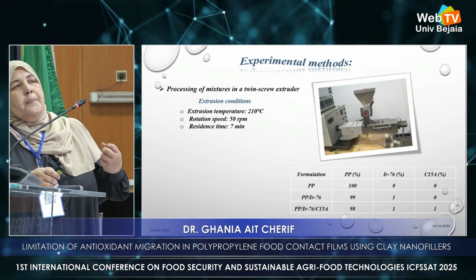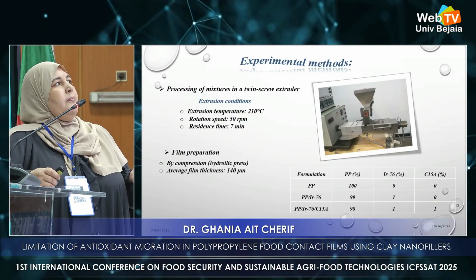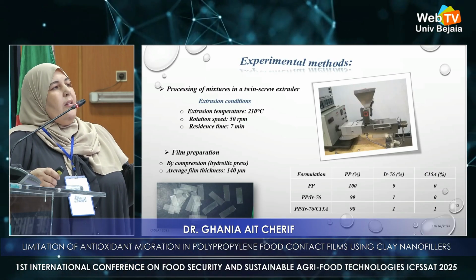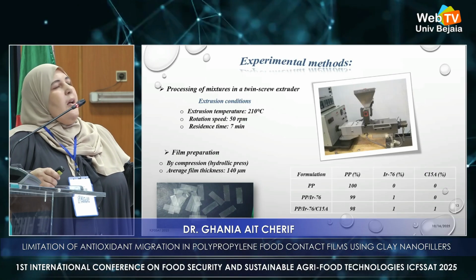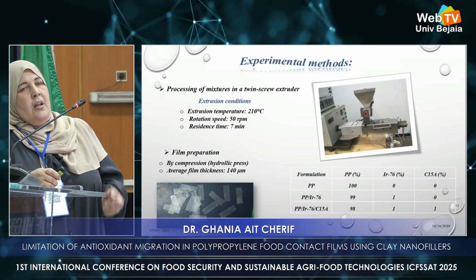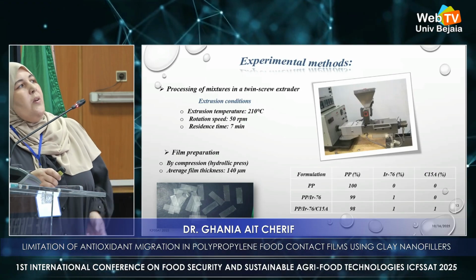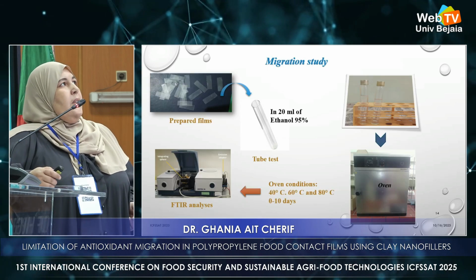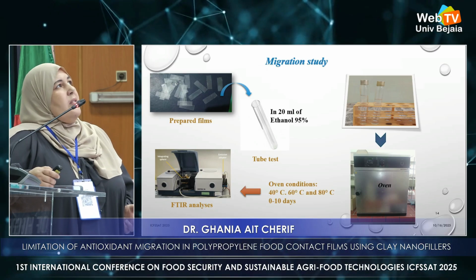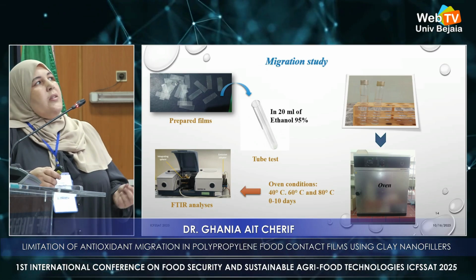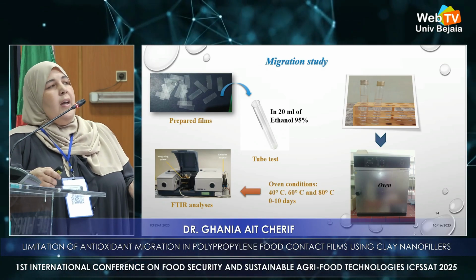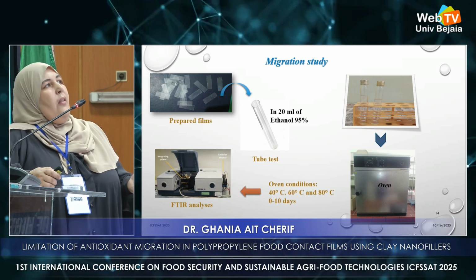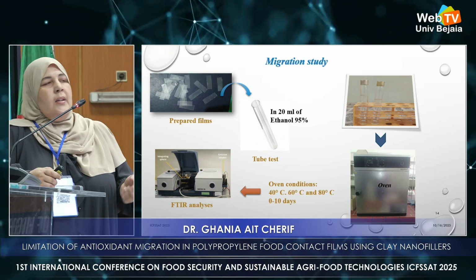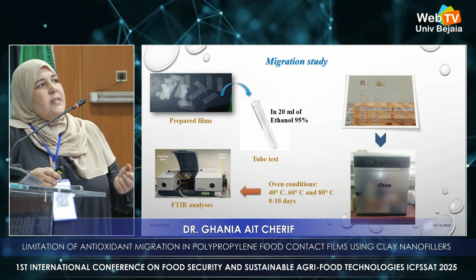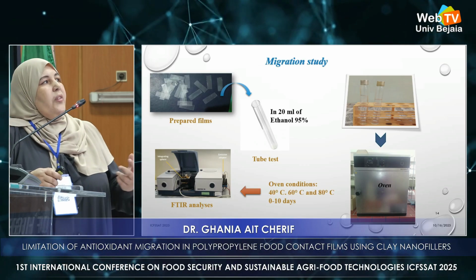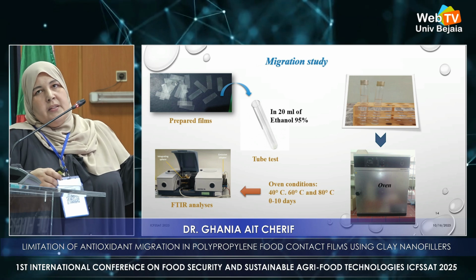All the materials were prepared in a twin screw extruder. After preparation, the films of these materials were prepared by compression with a hydraulic press. The average thickness of these films was about 140 micrometers. Migration study. For this migration study, each film was introduced in a test tube with 20 milliliters of ethanol at 95%. The sealed tube was introduced in an oven at different conditions of temperature and time. After the required time, each film was analyzed by infrared spectroscopy.